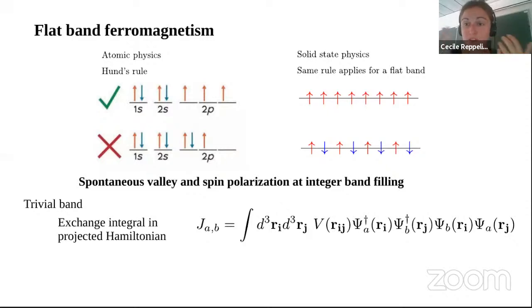and among the different terms you'll get, let's say, a Hubbard-U interaction. So you'll get a repulsion between electrons that doesn't depend on spin, but you'll also get an exchange integral, which favors the maximally polarized states. Maybe I should also say that this comes from the fact that the overall wave function has to be antisymmetric. You can think about it in terms of minimizing the Coulomb interaction. To do that, it makes sense to have wave functions that are antisymmetric in their spatial parts, and to keep the antisymmetry of the overall wave function, the spin part must be symmetric, so ferromagnetic.